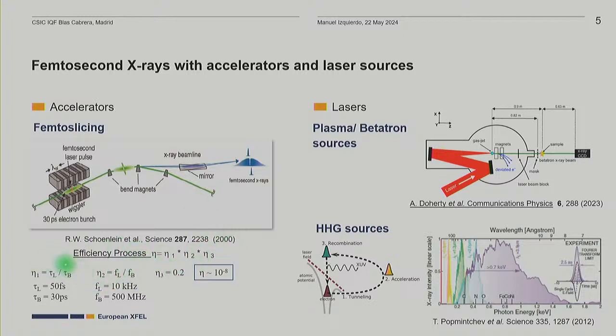The caveat of this is that it's a very low efficiency process, because the efficiency depends on three factors. One is the relative time duration between the laser and the electron bunch, which is in the order of 50 femtoseconds for the laser and 30 picoseconds for the electron bunches. Second, the repetition rate: these powerful lasers run at up to 10 kilohertz, and the synchrotrons normally run at 500 megahertz. And then there is a third factor linked to the efficiency of the interaction of the electrons with the laser. This results in an efficiency of 10 to the minus 8, so you end up having 10 photons per second that are usable for experiments.